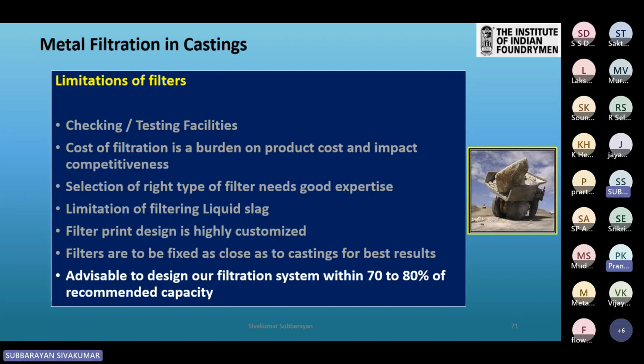It is my own experience that it is always advisable to design our filtration system within 70 to 80% of the recommended capacity by the supplier, because suppliers or manufacturers will always give the range as 100 kilos to 130 kilos. If you design the system for 130 kilos, it depends on how clean is your metal, how clean is your running system, how clean is your mold, all those factors. Even if you lose one casting because of filter breakage, you have to compensate with 50 castings. So it is always advisable, and we started practicing it, to design the system with a maximum of 80% of the recommended capacity.